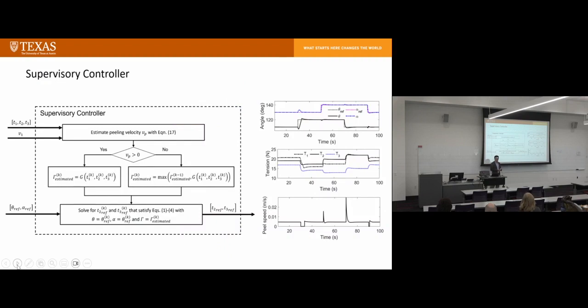So in the end, we developed a supervisory controller. For the model we have, we're using tension, and we also have an input variable, the input speed. Based on these four parameters, we estimate the peeling velocity VP. That VP is the peeling front velocity, so where it goes. Sometimes VP will stop, because if you didn't control the process well, there's no peeling happening. So the peeling front is going to shift to different positions. There's no stable peeling, and that's not desirable, because we want continuous peeling to give us controllable quality. If the peeling stops, then once it's resumed, it will generate some disturbance and generate defects in the peeling process.